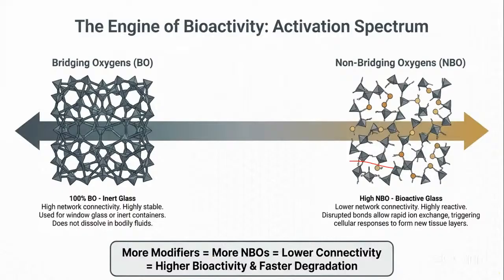On the contrary, if you go with higher NBO content, it starts interacting with the bodily fluid, and because of that, the bonds undergo ion exchange, and thereby it leads to formation of new tissue layers, or it also leads to formation of a hydroxyapatite layer for bone regeneration. So these are the two different things that you need to observe.